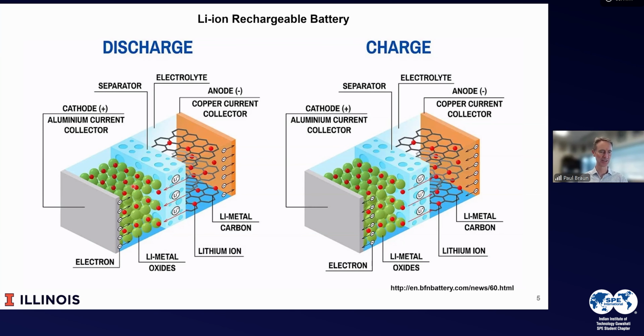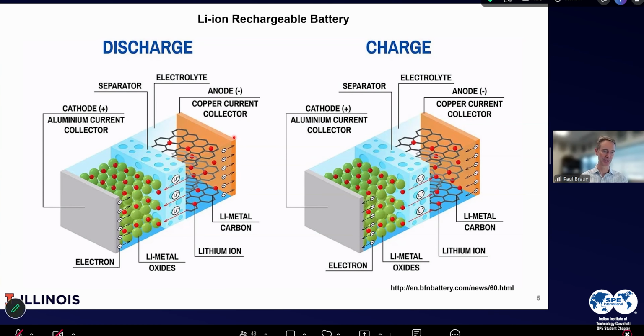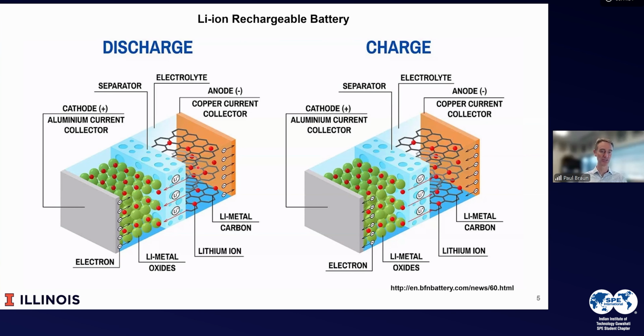One of the major challenges with batteries is that the lithium is a minority component. For each lithium atom, we have 6 carbon atoms. And if the cathode is, say, lithium cobalt oxide, and we can only extract half the lithium, we have 2 cobalts, 4 oxygens, and another lithium that we don't use. And then on top of that, we have current collectors, separators, electrolyte, and many other components. So really one of the goals here is how do we minimize all of these inactive or dead weight elements? And if we can do that, then we have a system that is higher in energy density and potentially lower in cost, because all of these other materials have real costs.